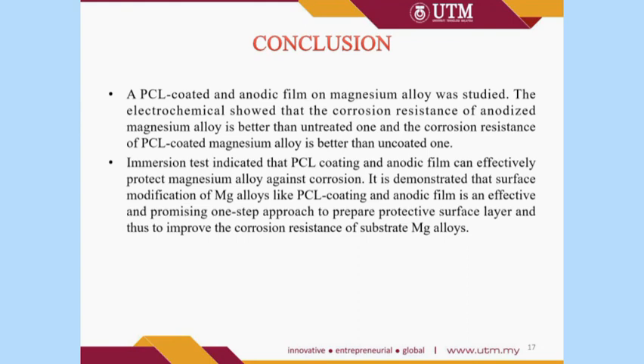In conclusion, a PCL coating and anodized film on magnesium alloy were studied. The electrochemical tests showed that the corrosion resistance of anodized magnesium alloy is better than the untreated one, and the corrosion resistance of PCL coated magnesium alloy is better than the uncoated one. Immersion tests also indicated that PCL coating and anodized film can effectively protect magnesium alloy against corrosion. It is demonstrated that surface modification of magnesium alloy like PCL coating and anodized film is an effective and facile one-step approach to prepare a protective surface layer and to improve the corrosion resistance of the substrate magnesium alloy.